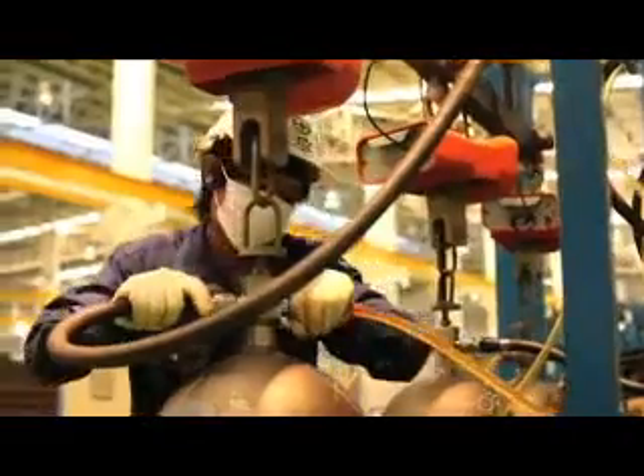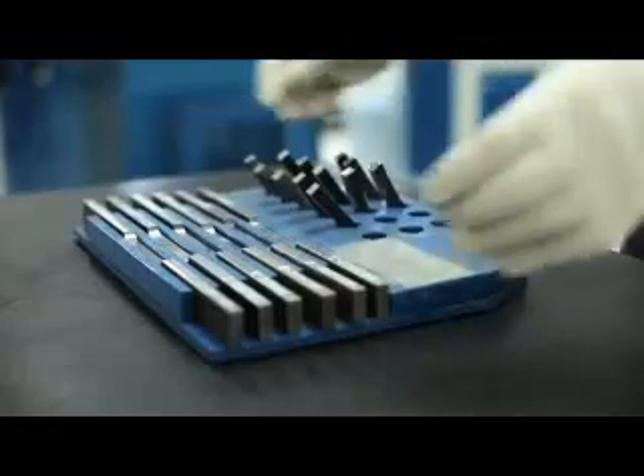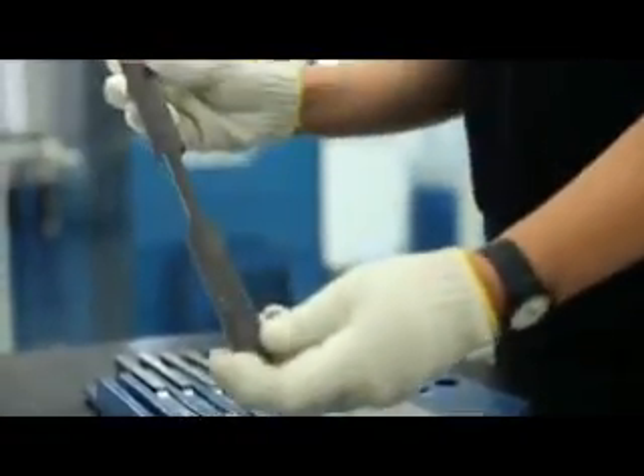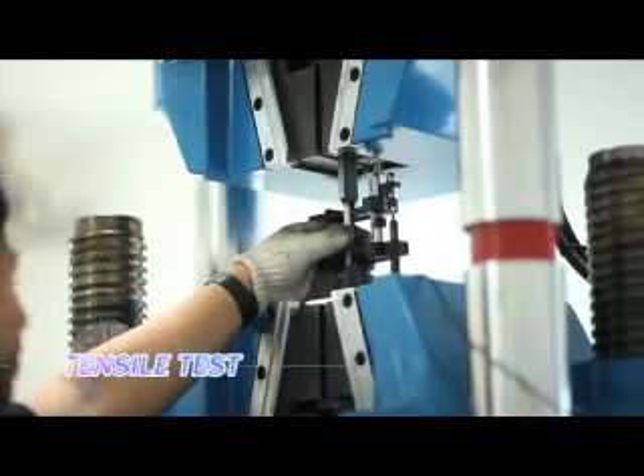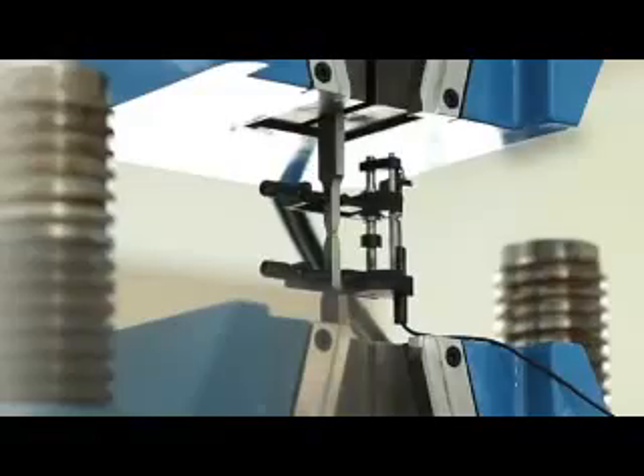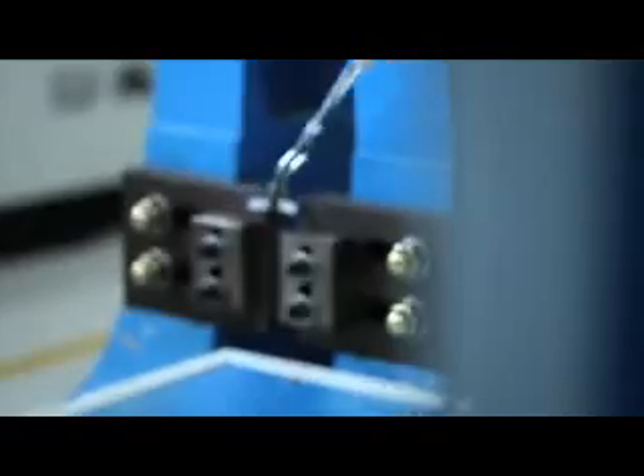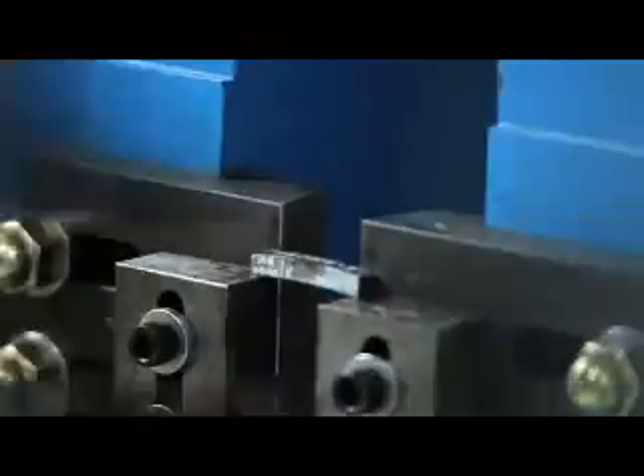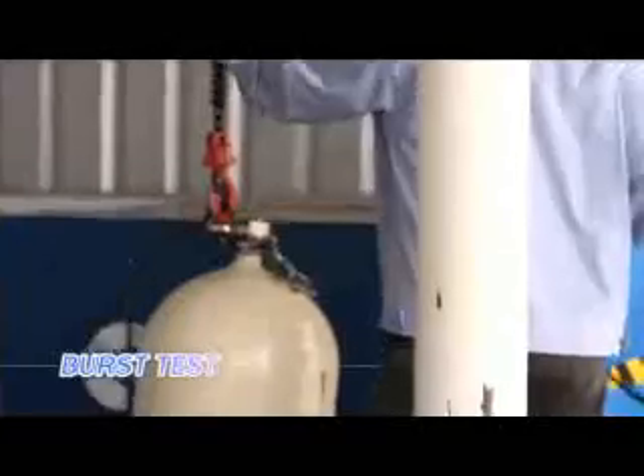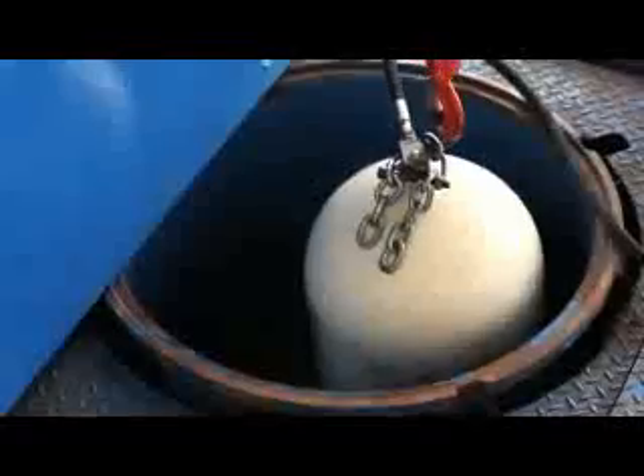Quality control system. Besides leak test, ultrasonic test, hardness test and hydraulic test, we also have other procedures to verify our product. Tensile test: measuring tensile and yield strength and elongation. Impact test: measuring absorbed energy by Charpy V-notch impact test at minus 50 degrees Celsius. Burst test: filling up pressure till the cylinder is ruptured.